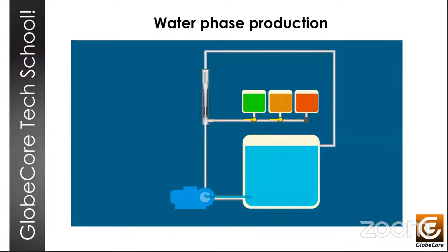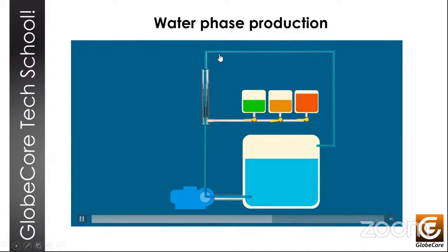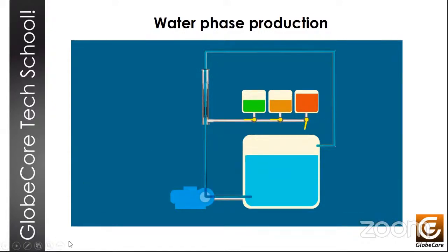As a result, we get a homogenized product at the entrance to the mill, mixed at the molecular level, and it's pretty much already a homogeneous liquid. The final homogenization and stabilization of the emulsion takes place in the mill, where we get the final product of the highest quality with the required parameters. So let's talk about the mills.